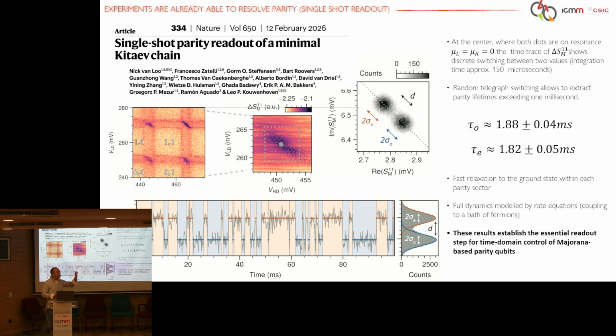The lifetime of this parity state is actually above milliseconds. This is a very long lifetime for a qubit, so this is very promising. We are very happy about this paper because this is very promising for a parity qubit, with millisecond lifetimes where you really see this kind of random telegraph noise signal. This is real-time data where you can resolve the parities very nicely, and the lifetime between stochastic events exceeds milliseconds, which is essentially infinite for a qubit. It's a very long lifetime.